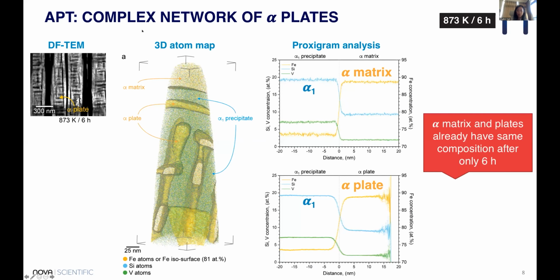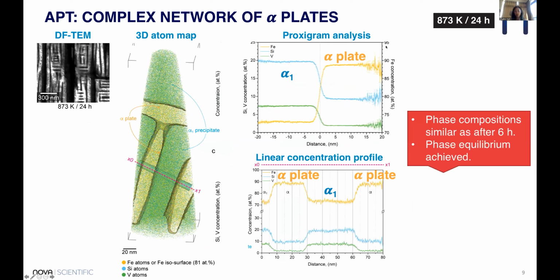After 24 hours of aging, the hierarchical alpha plates became much larger. This data set only contains alpha-1 precipitate phase with hierarchical alpha plates inside, also visualized using the 81 atomic percent iron isosurface. The proxigram analysis looks almost identical to that from the previous slide. We place a small cylinder perpendicular to the interface to extract a 1D concentration profile, shown here at the bottom. The 1D profile nicely reproduces the information from the proxigram, showing the composition of each phase with no changes observed. We conclude that phase equilibrium is achieved.